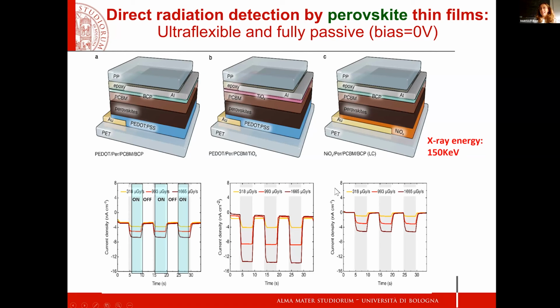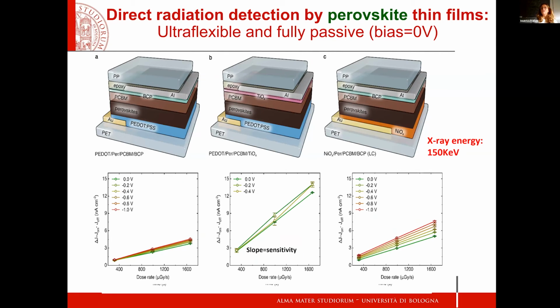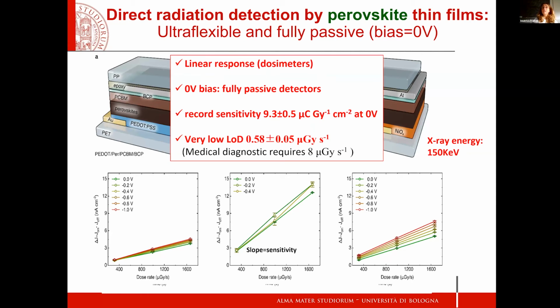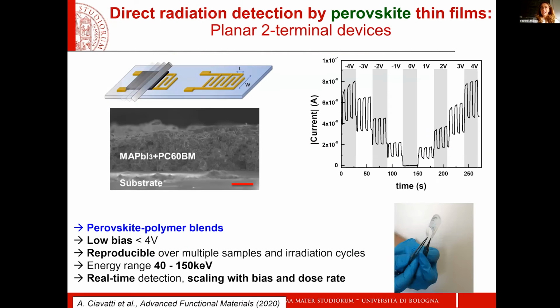That is very important, because here I'm reporting, just for example, 3 different structures with, again, same perovskite, different heterostructures. And you see that under the same X-ray beam, the response on-off is very different in terms of intensity, and therefore also the sensitivity, which is the slope, varies strongly. But again, these are very good because they are 0 bias, fully passive. So very good for large area and very good for wearable applications.